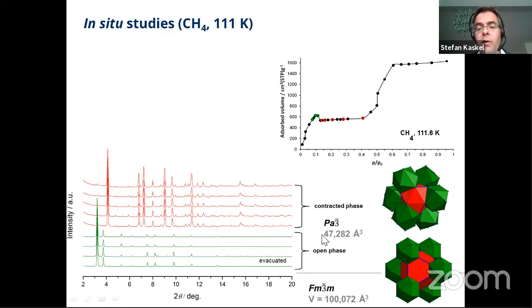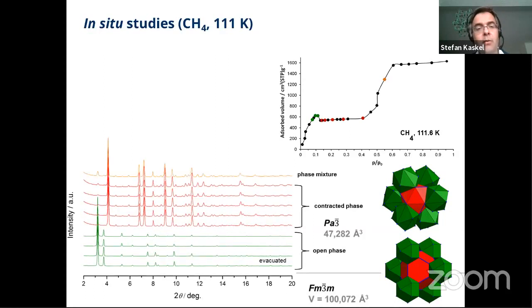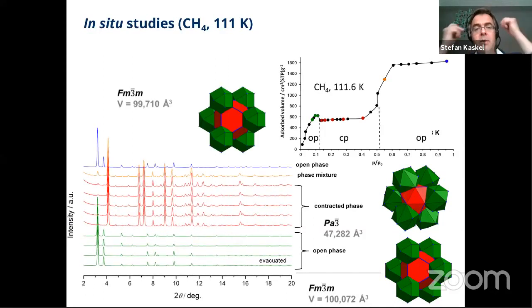So 47,000 cubic angstrom in this intermediate phase. We call this the contracted phase now. And we also do all the Rietveld refinement basically. And we see that this huge octahedral pore in the center is contracted to a micropore of less than 1 nanometer. And what happens at higher pressure is that the MOF is reopening again, and we see almost the original structure again, almost 100,000 cubic angstrom, and the pore is completely restored.